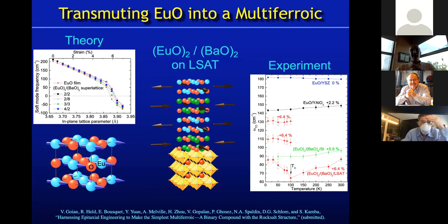But what they predicted is if you strain this thing enough, and in their calculations here, you can see the strains are huge. So they're saying that it's of order 6% strain, giant strains to get there, that you should be able to make the europium oxide simultaneously ferroelectric and ferromagnetic, similar to the europium titanate example that I talked about early on. To try to do such heroic strains is not easy, and my postdoc worked on this for years.